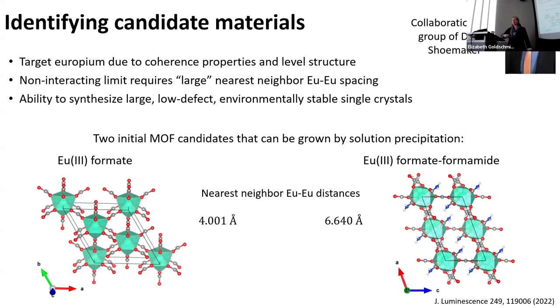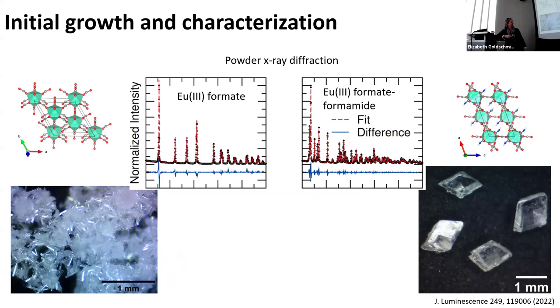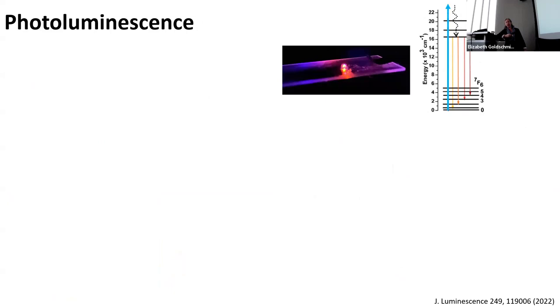In that paper, we showed some initial characterization. So what did we actually grow? We grew big formate crystals. We grew tiny formate crystals, but we grew them. They look about right when you do X-ray diffraction. We did photoluminescence, so shine a blue laser on and look at what comes out. That's a real picture of a material, super fun. Some of the crystals are really small, and if the student drops one and loses it, he just uses a blue laser pointer and does this until he finds it, because it lights up so bright.